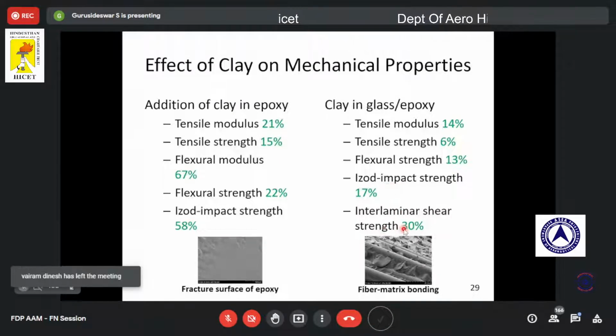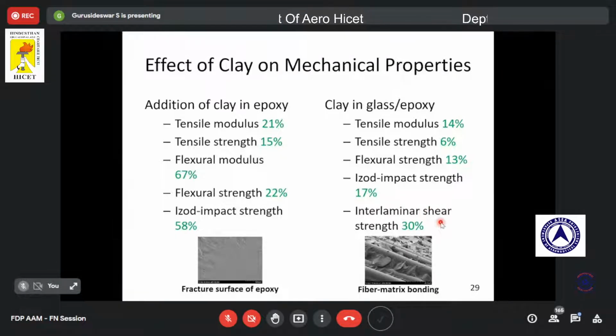So that's why we get a better improvement, because what we have done, the matrix has been dispersed with epoxy clay, right? The matrix epoxy has been dispersed with clay. So that is why we could see good improvement in matrix dominant properties like impact strength and interlaminar shear strength. But we could not get good improvement